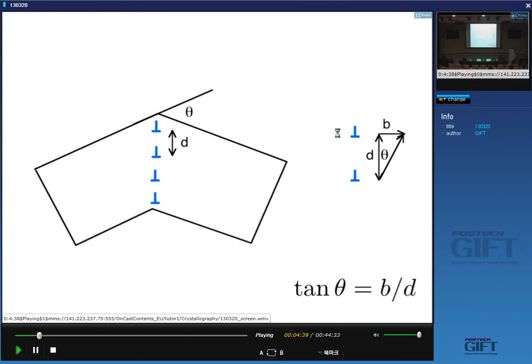So it's not just a model, but when you look in the transmission electron microscope, you will see dislocations if you look at a sufficiently high resolution. And you can work out the Burgers vectors of those dislocations by doing electron diffraction experiments, where you image using different diffracted beams. And when the dislocations become extinct, you know that your diffracted beam is 90 degrees to the Burgers vector, and then you'd find another extinction position. Taking a cross product, you get the orientation of the Burgers vector, right? So it's possible to determine not only the line vector, but also the Burgers vector.